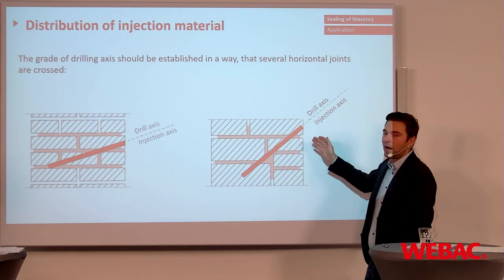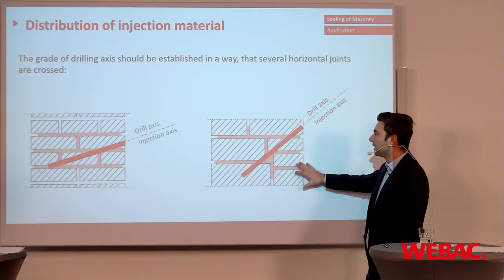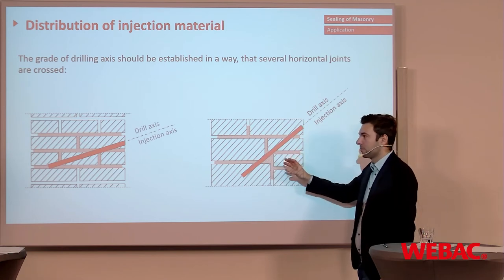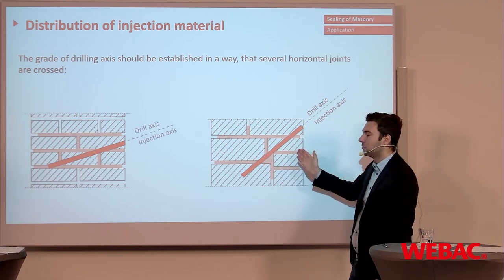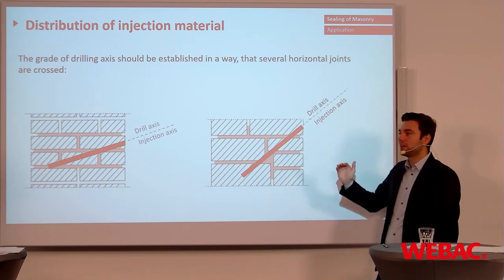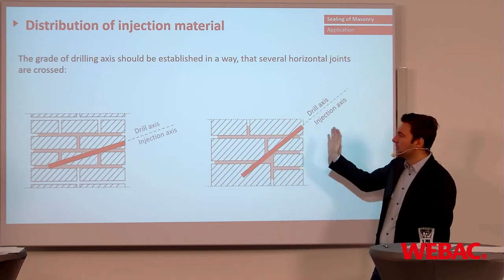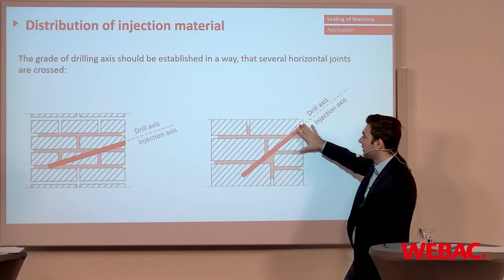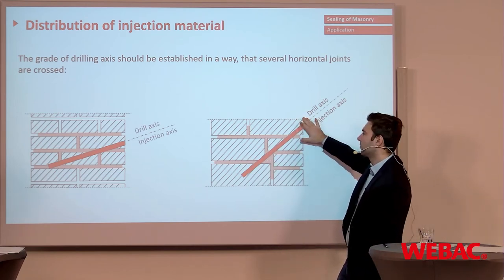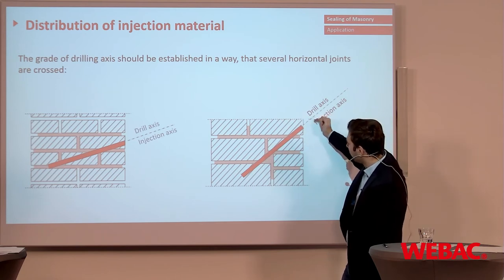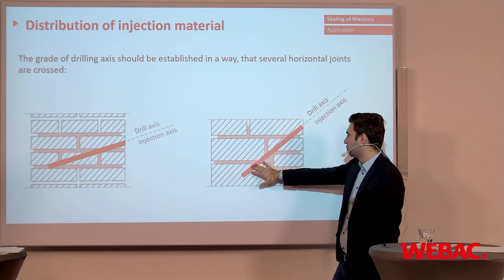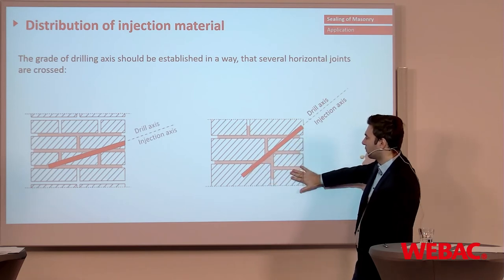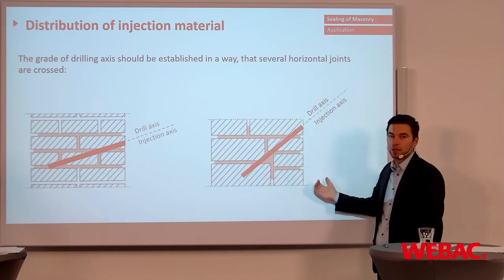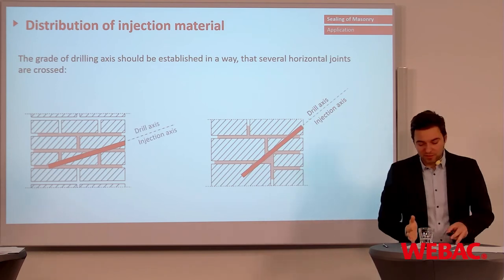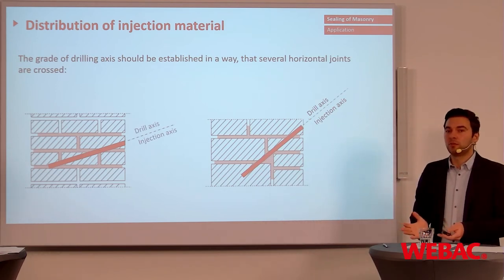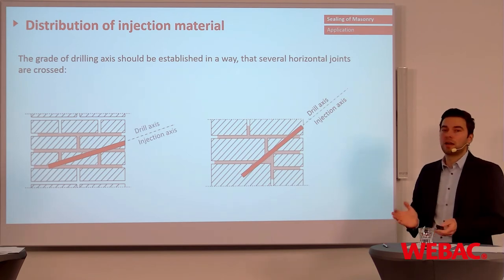If you have uneven masonry with smaller and bigger bricks, then for sure it might be necessary to adapt your drilling angle. It can be slimmer, it can be above 45 degrees, but still the target is to hit as many joints as possible, and you can see it here. With one drilling, you hit one and two main joints and two further joints where the material is able to penetrate. So therefore, it's always necessary to see what kind of masonry do I have and how do I have to drill?